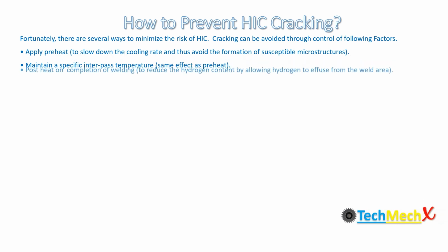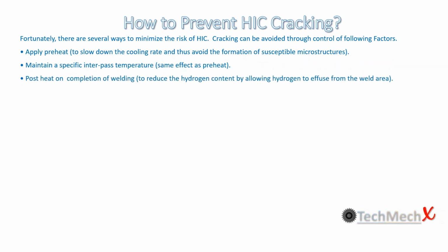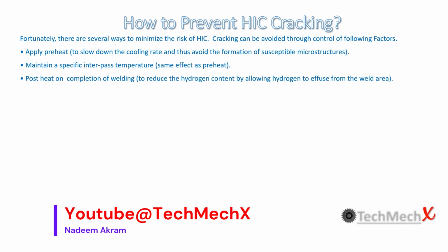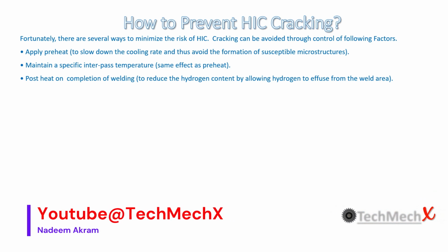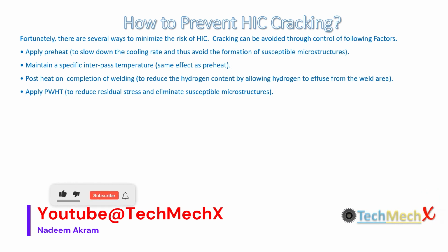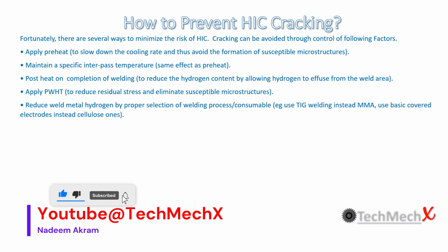Apply post-heat on completion of welding to reduce the hydrogen content by allowing the hydrogen to effuse from the weld area. One point to be noted: this is post-heating, which is done to diffuse hydrogen out of the weld area. This is not PWHT, or post weld heat treatment, which is done to reduce the residual stresses. The next point is to apply PWHT to reduce the residual stresses and eliminate susceptible microstructures. Reduce weld metal hydrogen by proper selection of welding process, consumables, etc.